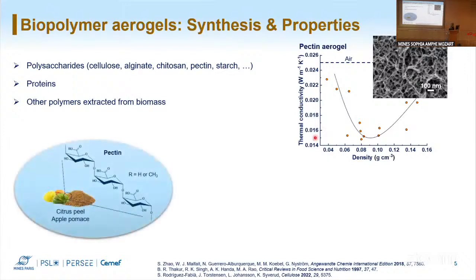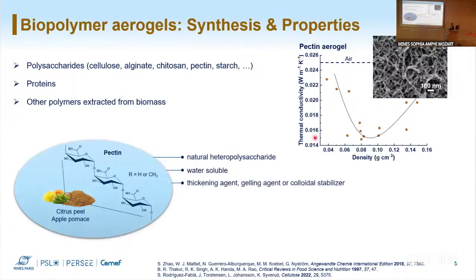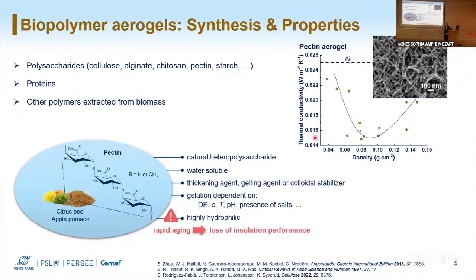Pectin is usually extracted from citrus peel and apple pomace that comes from waste from the industry. It's a natural heteropolysaccharide. It's water soluble. It's used in the food industry for its gelling properties, and these properties depend on the degree of esterification of pectin, on the pH of the solution, and other parameters. Pectin, because of its structure, is highly hydrophilic, and when we want to use it for materials engineering, we notice that there is a very rapid aging, a problem that we see with a lot of biopolymer aerogels, and we have loss of the insulation performance that we can see in the graph above. So the first question that we have in my thesis is how to make pectin hydrophobic.